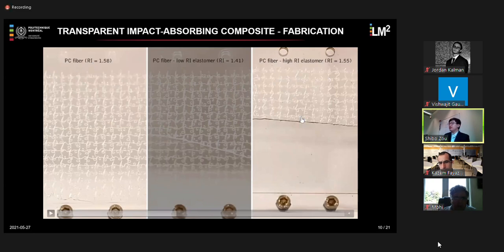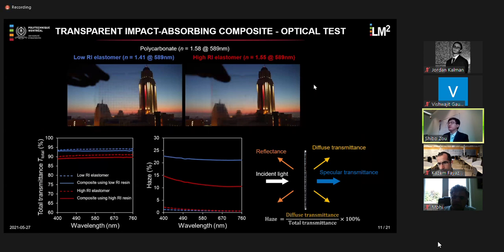So that's why you can see with the better matching on the refractive index, the fiber almost disappears in the resin, and this gives us a better transparency. So we also did optical tests on these two kinds of composite based on different elastomers with different refractive indexes. It shows that the optical transmittance of both composites is around 90%. So it has high transmittance.